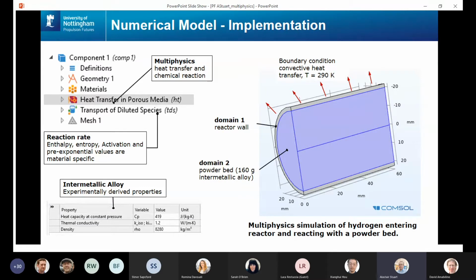So my reactor is described on the right-hand side in the domain, and in the grey is the metal cylinder. I've sliced the cylinder in two to minimize the amount of computation. I'm showing in the blue domain, which is domain number 2, the intermetallic alloy in its powder form. For this particular model, I'm suggesting there's 160 grams. Now, I haven't had to make the powder to that scale, but my model can predict the performance of it as a powder bed in this container.